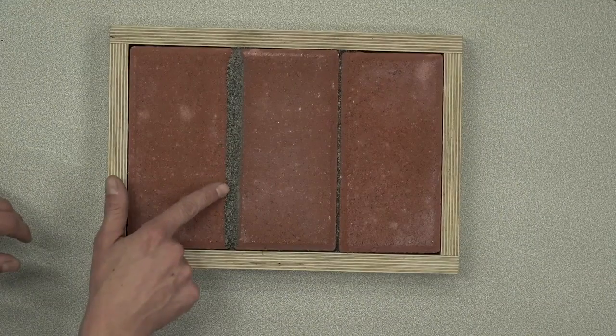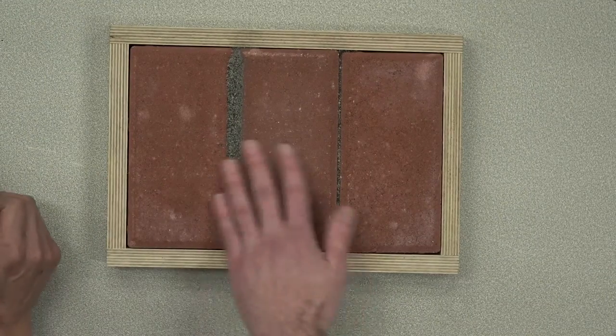Well, one last reason why we do it is actually the watering process, right, AJ? Exactly. So again, these things tend to chain link into the next thing. If your joint's filled all the way up to the top, and we start watering it, where's that water go? It's going to shed off. It's going to be running off everywhere. The surface, yeah. Yep. If we've got this nice chamfer that almost channels the water into the joint, well, that seems perfect. You get a little bit of water to sit in there and drain into the joint and activate a sufficient depth.